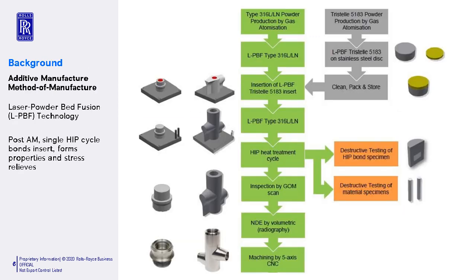So how does the AM method of manufacture differ? So again, we start off with stainless steel and Tristelle metallic powder produced within our supply chain via gas atomization. This is sieved then to the specification powder size requirement. We then start the build with the Tristelle inserts, and these are built on stainless steel discs using laser powder bed fusion additive manufacture technology. These are then cleaned, packed, and stored for later use.